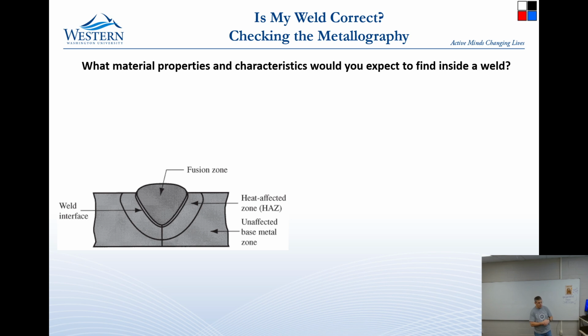You can get somewhat rid of the heat affected zone if you can take the entire structure up to the austenitic zone and then bring it down and do a heat treatment on the whole structure. But that's very hard to do because the materials around the weld will react differently to the weld because they have different thicknesses.